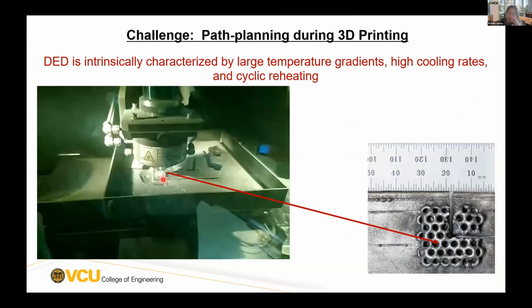Well, if it did play, you'd notice it was pretty interesting, because the laser head doesn't move in one direction, it doesn't raster. It moves in a very complicated fashion while printing the 3D structure, and that's by intention, because DED is intrinsically a non-equilibrium processing technique with large thermal gradients, high cooling rates, and cyclic reheating as we build layer by layer.